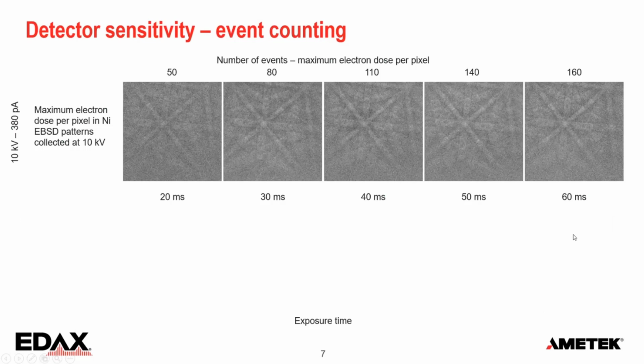Now, just to show you the effect of the number of events and how long we have to measure, this is a sequence of patterns at 10 kV with about 380 picoamp of current. And when we then expose for 20 milliseconds, we get a maximum dose per pixel of 50. And on average, that is going to be between 10 and 15 electrons anywhere on the sensor. So we just increase the exposure. You can see the number of electrons increasing, and also the contrast in the pattern is coming up. So we start to see more and more detail.